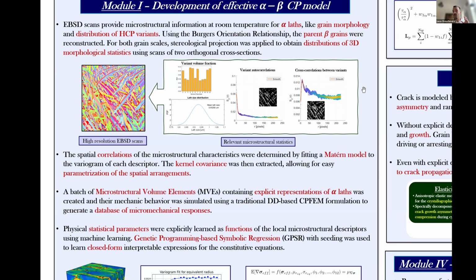So what we do is characterize this microstructure in terms of distributions, so that we describe this microstructure through parameters. For instance, a distribution of grain size, volume fractions of the different HCP variants, so the different crystallographic orientations of the crystals, and the correlation between the variants and the positioning of the defects to the microstructural grains.